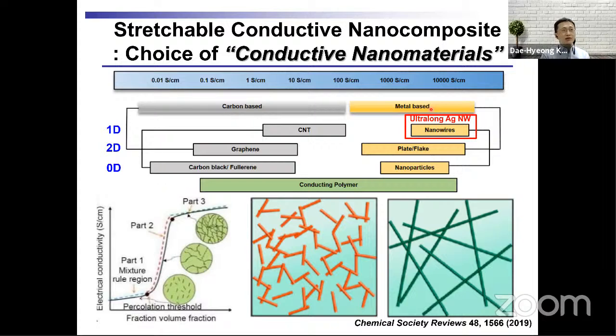And in particular, if we can use ultra-long silver nanowires, then we can minimize the percolation threshold of the conductive network. In other words, with a small number of nanowires, we can make a conductive pathway of the nanowire network. So we chose ultra-long silver nanowires as a conductive filler.